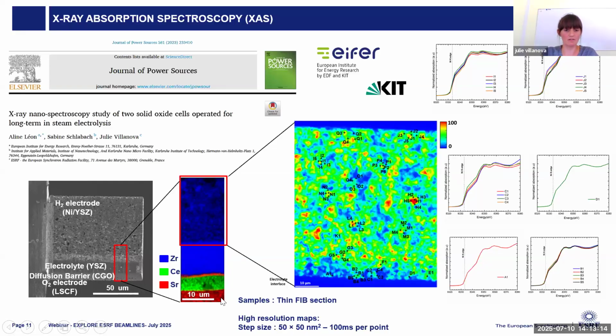But what we see on this sample, this cell that worked for 6,000 hours, I think, is a migration of this strontium to the interface with the electrolyte, which is detrimental for the electrochemical reaction. What we also saw on the hydrogen electrode side, where we have the strontium, but here what is represented is the nickel distribution, is a depletion of the nickel at the interfaces. On top of that, we also tried to determine whether one of the degradations is the reoxidation of this nickel. By pointing at all these black spots and performing a XANES measurement by scanning the energy around the K edge of the nickel, we were able to say, okay, in this position I still have nickel metal, or here I have a reoxidation.